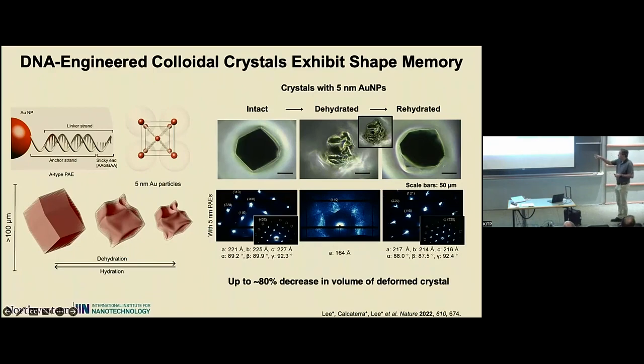And one of the things we discovered with the rhombic dodecahedra, for example, the BCC architecture, is that if we dehydrate these they will just crumple like an accordion. Okay, and they'll go from a lattice parameter of tens of nanometers down to a single nanometer. And you lose, for the most part, almost all the order in the system. But if you rehydrate them, they go right back to the crystal. This isn't disassembling and reassembling. It's compressing, completely losing order, and then the number of particles in the box, so to speak, remain constant, and you resolvate. And this is where the DNA is not just acting as a glue to hold the particles together, but as a true blueprint to say, go back to that BCC architecture.